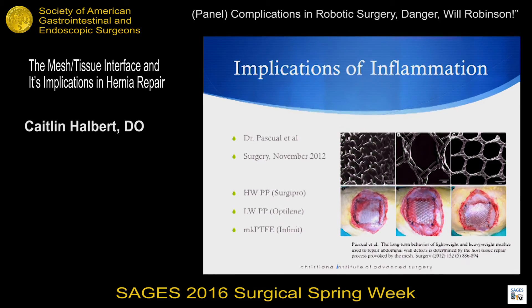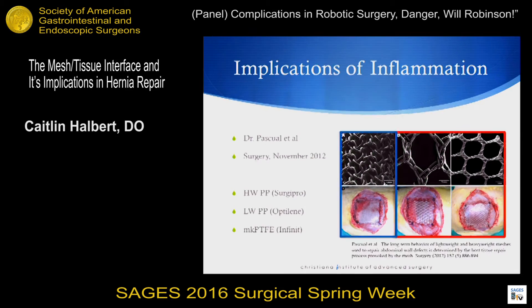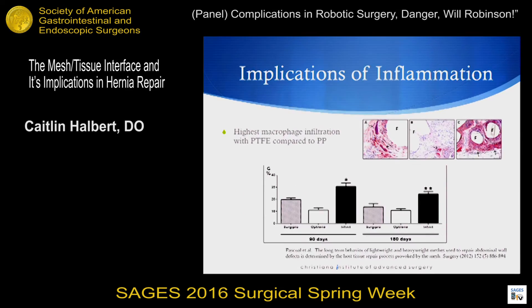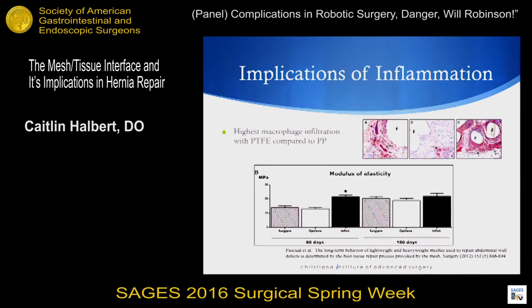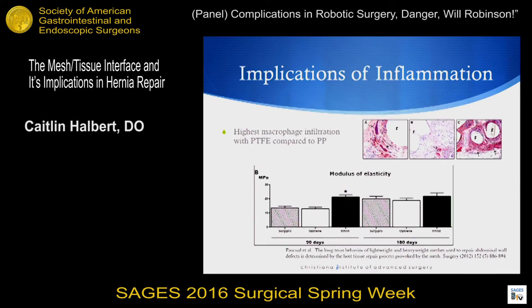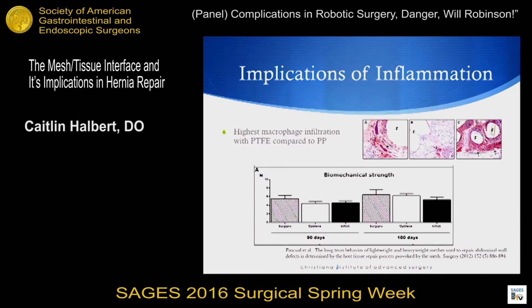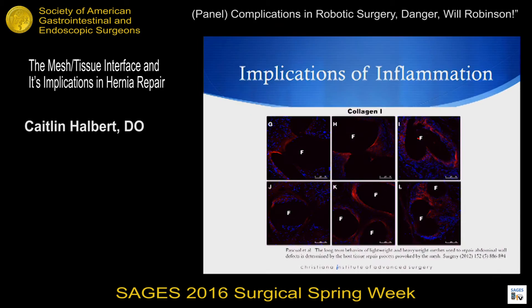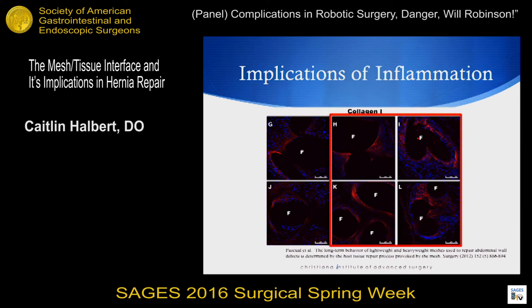This 2012 study looked at polypropylene and compared it to the monofilament knit PTFE, which really looks like a large pore mesh. On the left is the heavyweight polypropylene, and on the right the lightweight and monofilament knit. They found that the PTFE did drive a lot of early inflammatory changes in comparison to polypropylene. But long-term, looking at the modulus of elasticity and tensile strength, it really started to become equivalent further out — at 180 days there was no significant difference between the meshes, and this was also consistent with the biochemical strength. They also looked at collagen reorganization: collagen type 3 getting replaced by collagen type 1 shows maturity of integration, and you can see a significant amount in the large pore polypropylene as well as the monofilament knit PTFE.